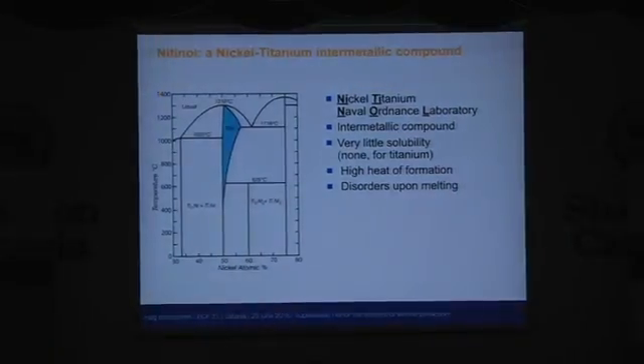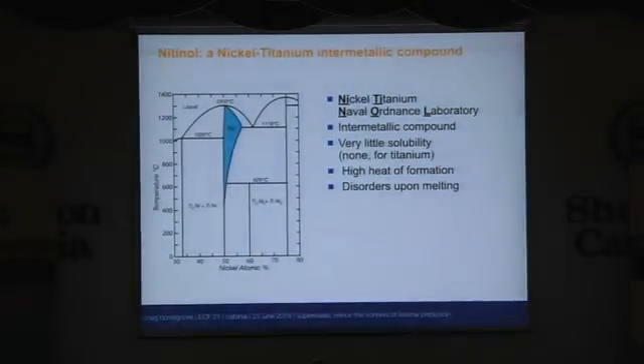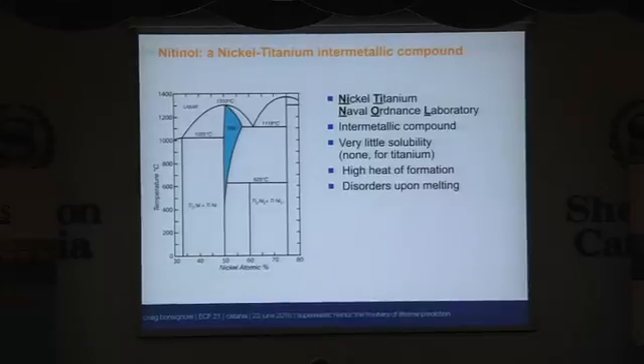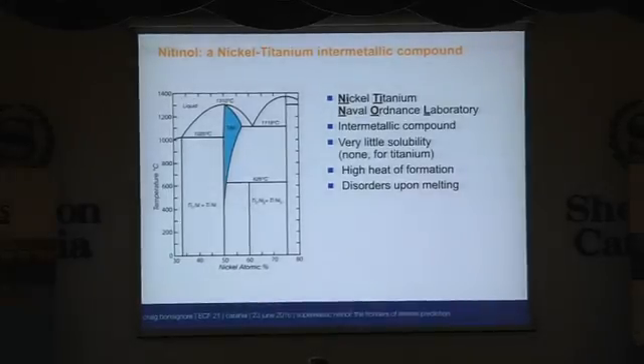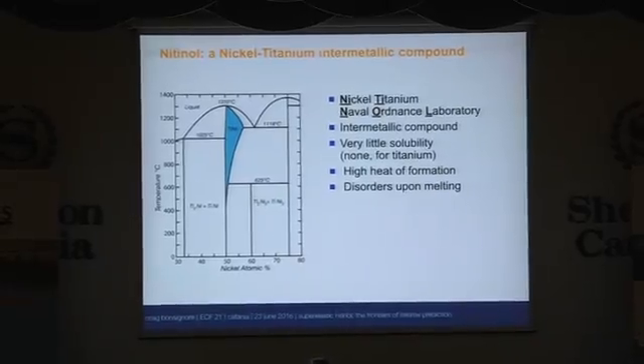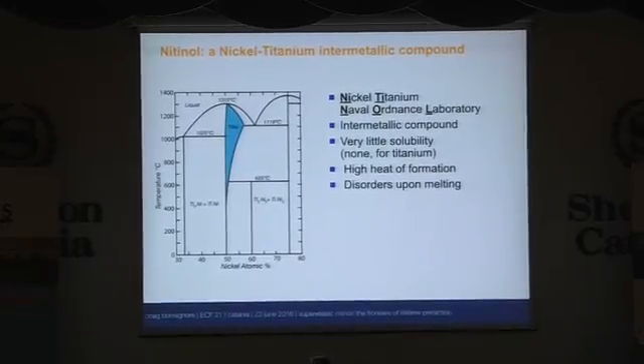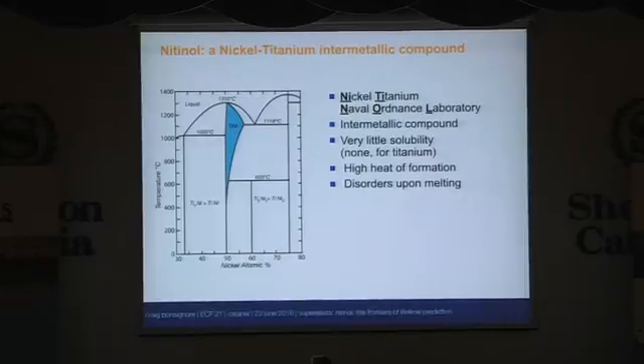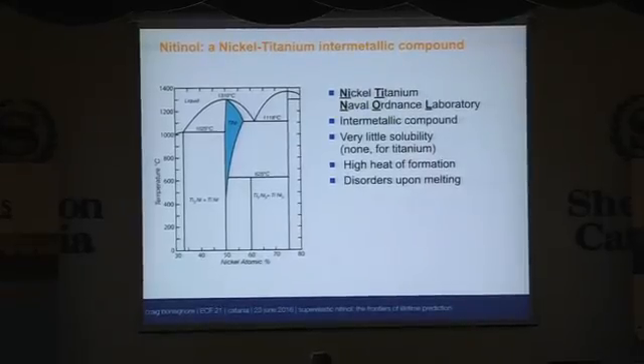So, just briefly, what is Nitinol? Nitinol is a nickel-titanium intermetallic compound. We often say that it's an alloy because that's a convenient word, but strictly speaking, it is an intermetallic compound, which means that the nickel and titanium atoms, of which there are roughly half and half, need to be in very specific places in a lattice or a matrix for the sort of magic of this material to work.